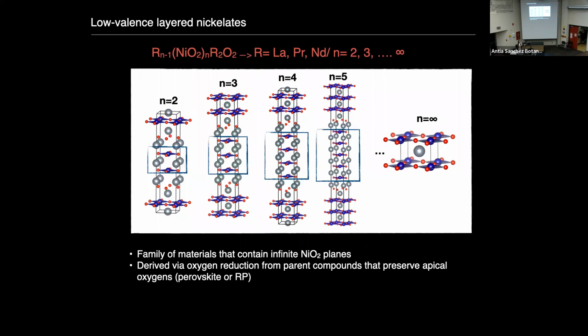Unfortunately, these materials cannot be synthesized directly in this very nice layered form, but one actually has to get here from parent phases that do have apical oxygens. The reason for that is because nickel is not very happy being in a 1+ oxidation state, even though that's what we want. You have to get here again from parent phases in which nickel is a little happier. And then our experimental colleagues are able to do all of this alchemy to remove those apical oxygens out and end up with these nice layered cuprate-like phases, which is what we want.